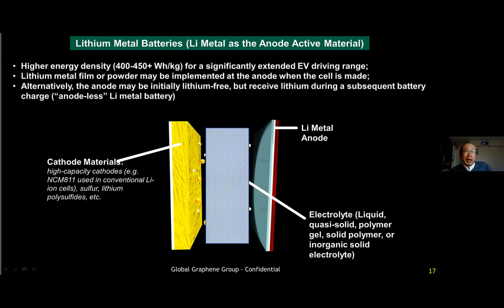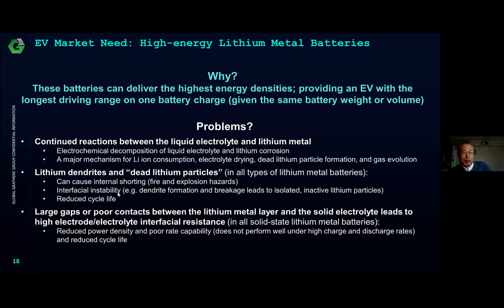One problem is that there is continued electrochemical reaction between the liquid electrolyte and the lithium metal itself. Also there is the so-called lithium dendrite issue, or so-called dead lithium particle issue. And then in solid state electrolytes, there is a large gap or very poor contact between the lithium metal layer and the solid electrolyte separator, and that leads to very high internal resistance.